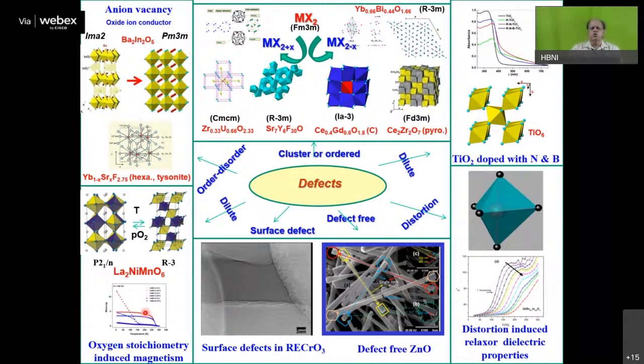Third approach which is going to be taught to you is defects engineering. You will be surprised to know, many of you might be knowing also, point defects are very crucial for the existence of some materials. Some materials exist only because of the optimum extent of point defects. The classic example is yttria stabilized zirconia. Unless you introduce oxygen vacancies, the cubic form of YSZ will not exist. At best, you can get tetragonal yttria stabilized zirconia, which is also called partially stabilized zirconia. But for full stabilization of zirconia, you need to introduce some oxygen vacancies. And the thermodynamics behind this is, as you introduce defects, you increase the disorder, you increase entropy, and in turn, you attain what is called entropy-induced stabilization of metastable phases.